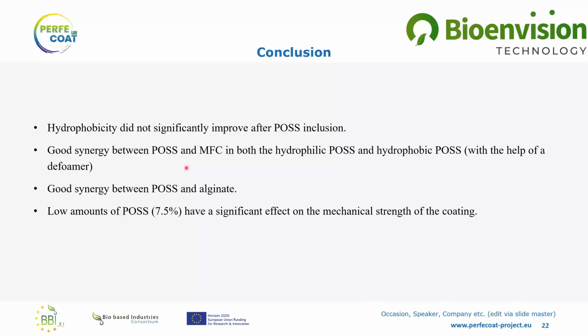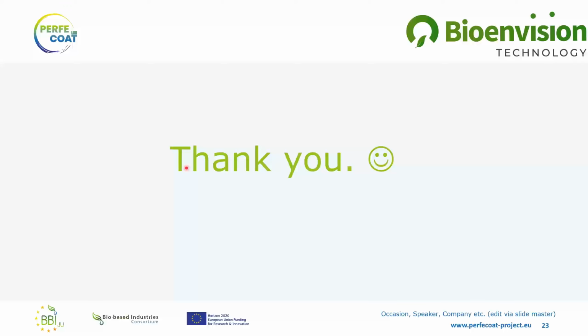In conclusion, we see that the hydrophobicity did not significantly improve after POSS inclusion, while there was good synergy between POSS, both the hydrophilic and hydrophobic POSS, and MFC, and there was also good synergy between POSS and alginates. And low amounts of POSS have a significant effect on the mechanical strength of the coating. Thank you for your attention.